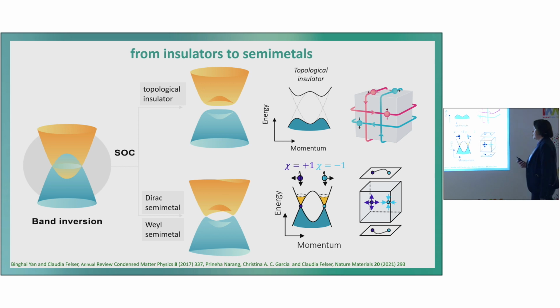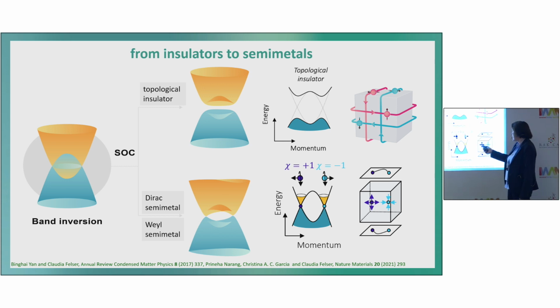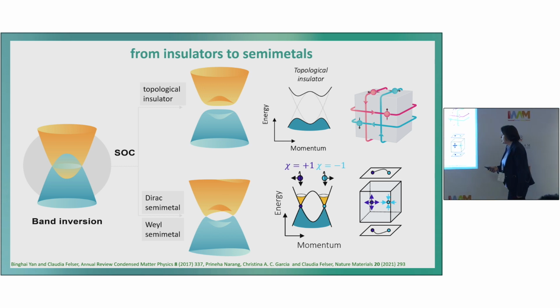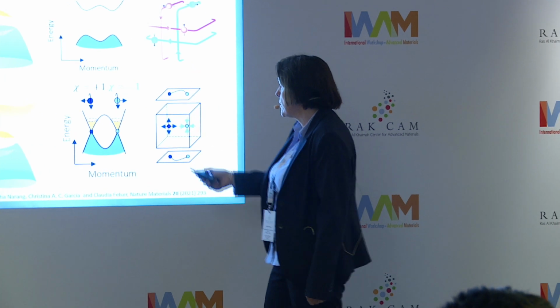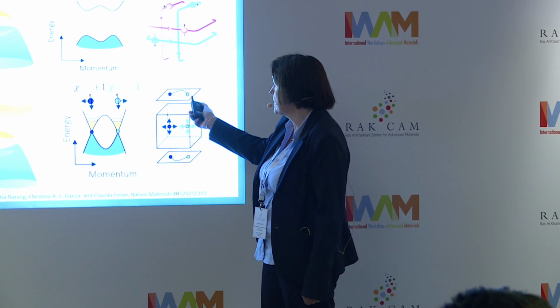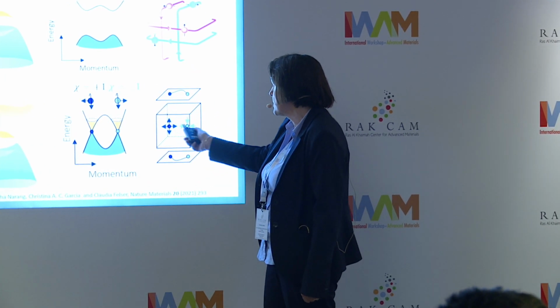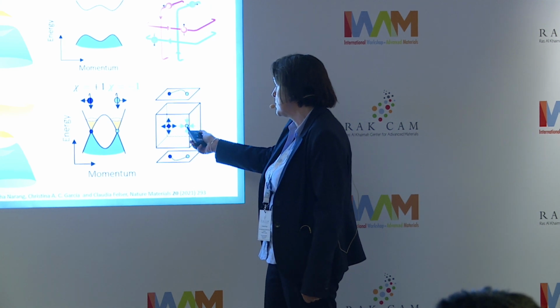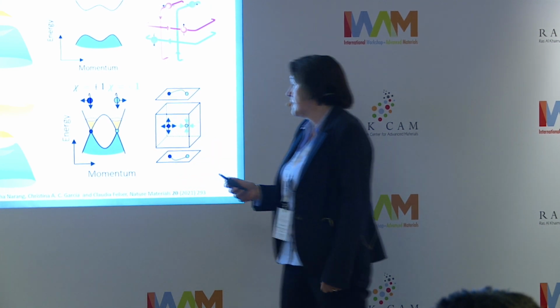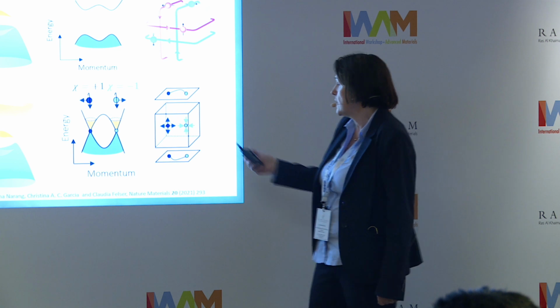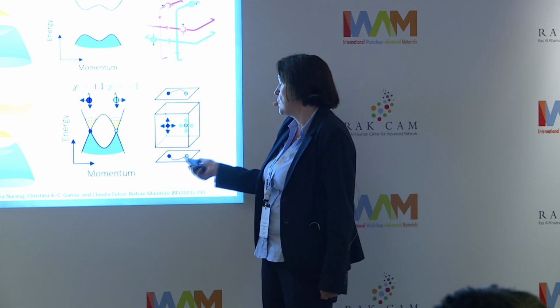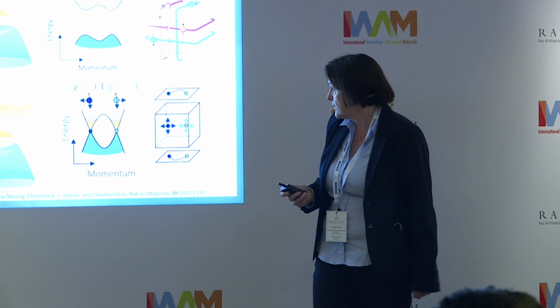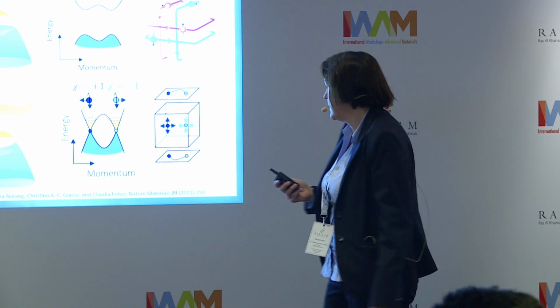And this leads to, if we have our crystals, in the bulk electronic structure, these Weyl points, and this also has a bulk boundary correspondence. In this sense, we now have Fermi arcs, because this system is topological between these two points in the electronic structure, and so the surface states are Fermi arcs, and they are connected through the different surfaces of the crystal.